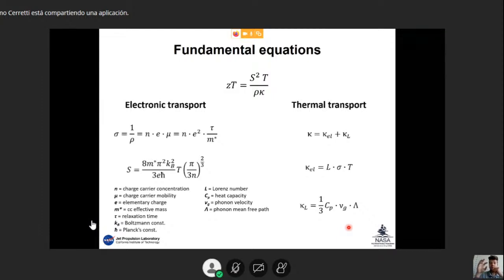Then there's the lattice thermal conductivity, which relates only to that part of heat which is carried through phonons, the vibrations of the crystal lattice of the material. So it's just dependent on the crystal structure of the material, and it's a function of the heat capacity, the phonon velocity, and the phonon mean free path.